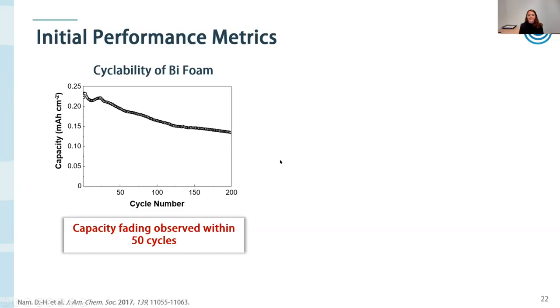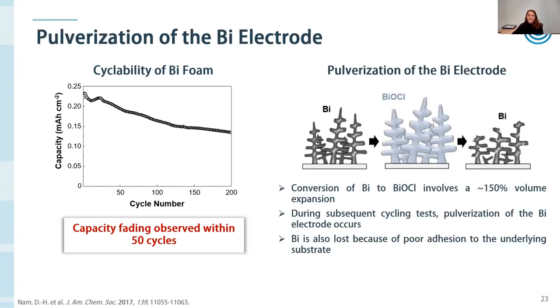This is actually what happens in traditional batteries as well, and is the reason that you need to charge your battery more frequently as it ages. But this was not a great first step as we started to look at our new desalination process. And the first thing that we did is try to understand why we saw this capacity fading. And what we found is that during the conversion of bismuth to bismuth oxychloride, we actually have a volume expansion of about 150%.